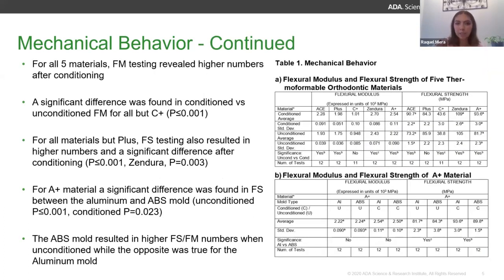So for our results for all 5 materials, we found that flexural modulus resulted in higher numbers after conditioning. We found a significant difference in conditioned versus unconditioned for all of them but C+. For all materials but C+, the flexural strength testing resulted in higher numbers and a significant difference after conditioning. And for our A+ material, we found a significant difference in flexural strength between the aluminum and the ABS mold. Overall, the ABS mold resulted in higher flexural strength and flexural modulus numbers when they were unconditioned, and the opposite was true for our aluminum mold. So we had higher flexural strength and flexural modulus numbers with conditioned specimens in our aluminum mold.